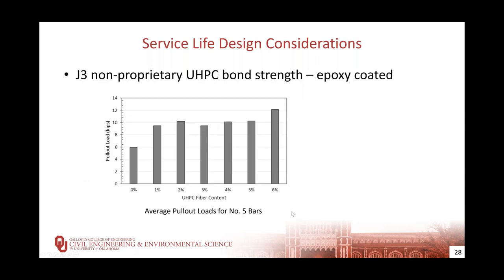This graph shows pullout loads for epoxy-coated number 5 bars with varying fiber contents. Again, the pullout load increased significantly from the 0% fiber case when 1% fibers were included, but little gain was seen for additional quantities of fiber, primarily because most specimens failed due to separation of the epoxy from the reinforcing bars. This effect of the epoxy can also be inferred from the lower pullout loads compared to the black steel bars.